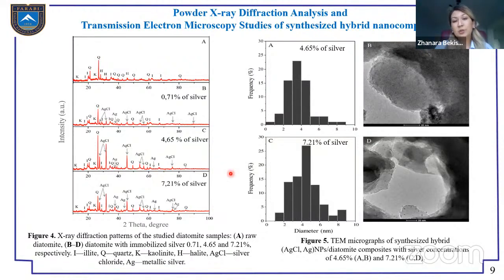And for the size distribution of nanoparticles by transmission electron microscopy, we can see uniformly distributed quasi-spherical nanoparticles with predominantly size from 2 to 5 nanometers. Also, there are nanoparticles from 1 to 2 and from 8 to 10 nanometers with a different concentration.